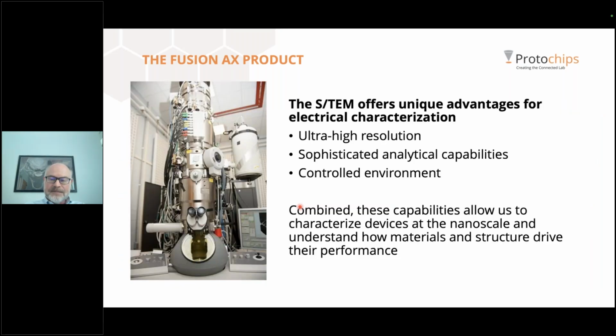First, the TEM or STEM. So here, the optics are much more than a stereoscope that you might find on a normal probe station. And they offer unique advantages for in situ electrical characterization. Now, first, of course, you can take ultra high resolution images of your sample. Next, in addition to the optics and the camera, the tool usually includes a set of sophisticated analytical capabilities like EDS, EELS, or 4D STEM. And these give you way more insights into your sample beyond just images, like composition, oxidation state, or electric fields.